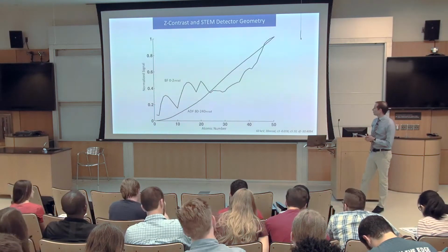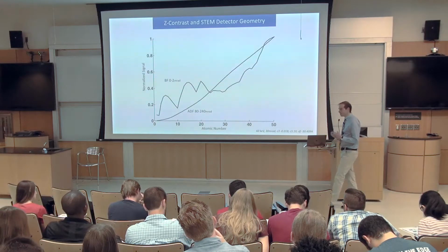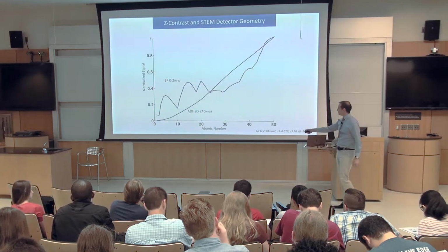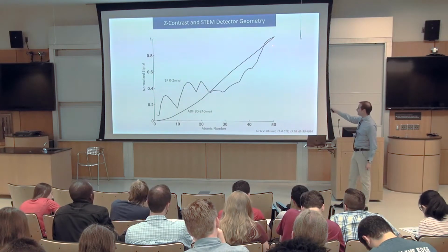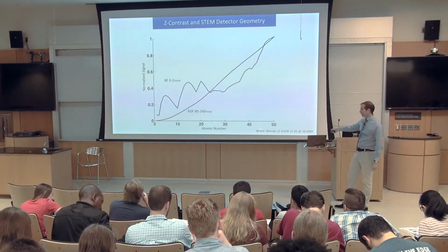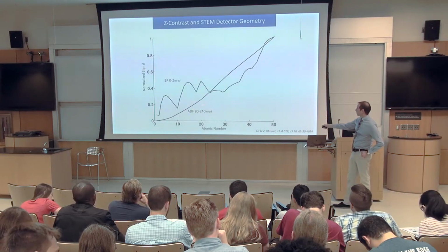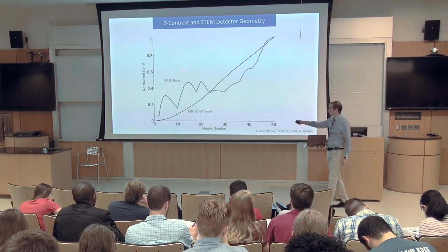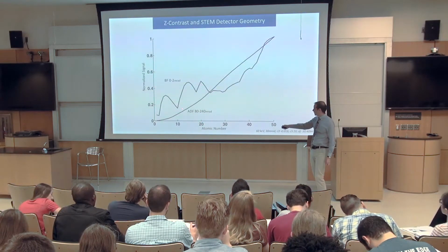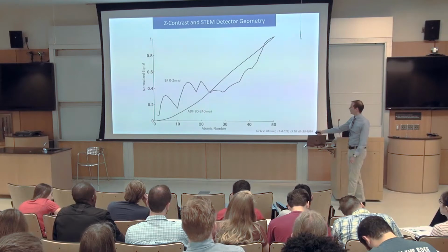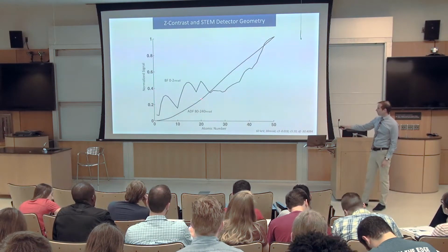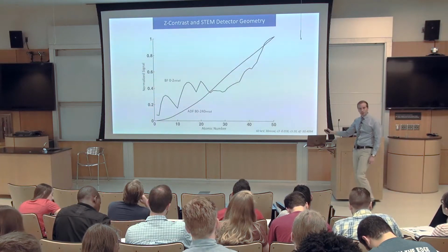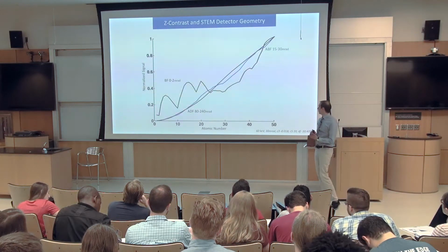Okay, so we like to work with annular dark field STEM because it meets this incoherent imaging condition, because it gives us Z contrast. We get very interpretable intensities that increase with atomic number. So we have a monotonic increasing function in the case of ADF, but in the case of bright field STEM, the coherent imaging mode, the intensity fluctuates rapidly. So we can try to infer chemical information based on the Z contrast with STEM, but it's certainly hopeless in the case of bright field.